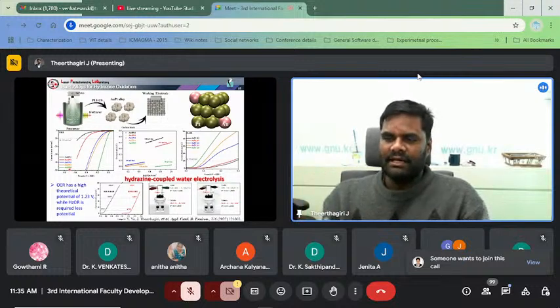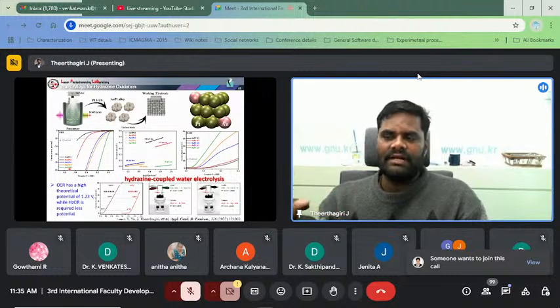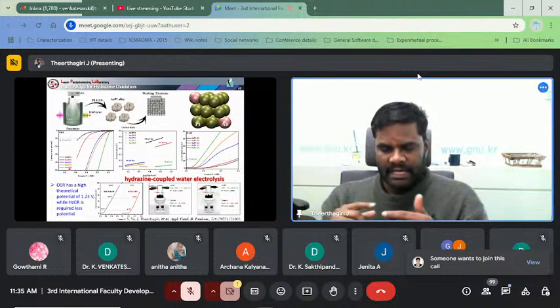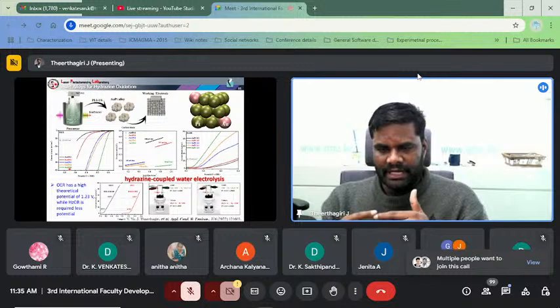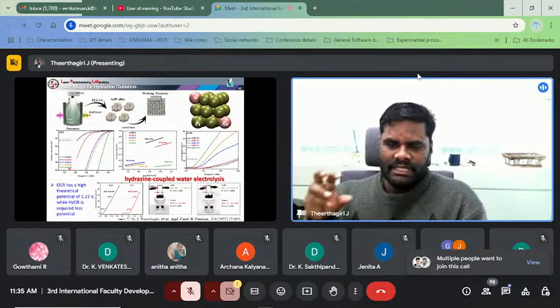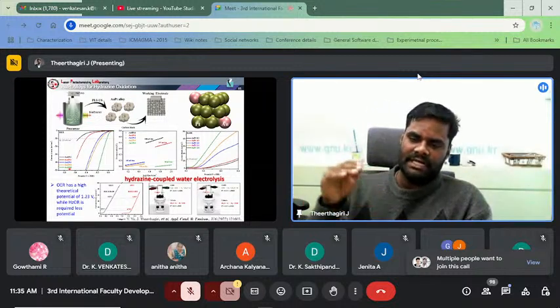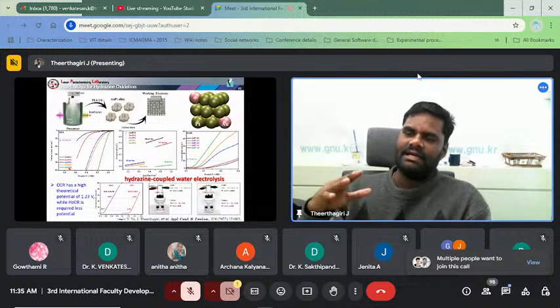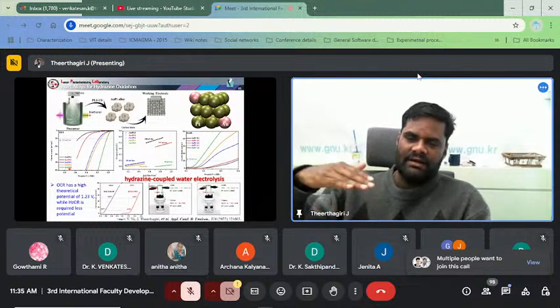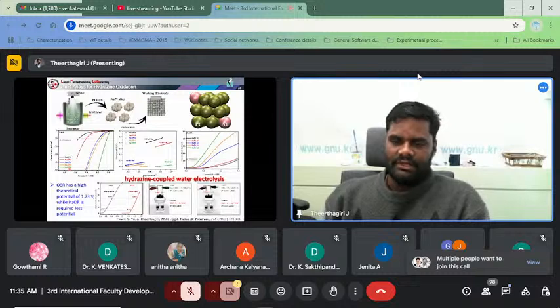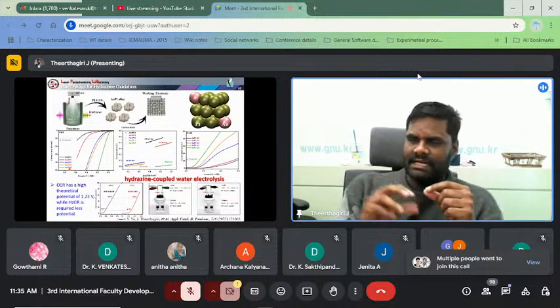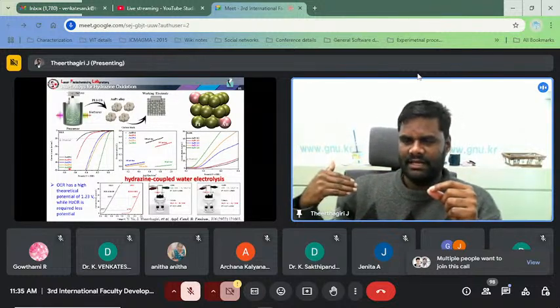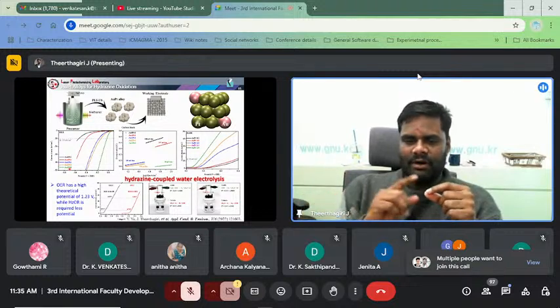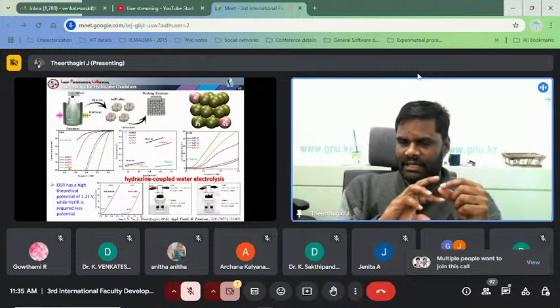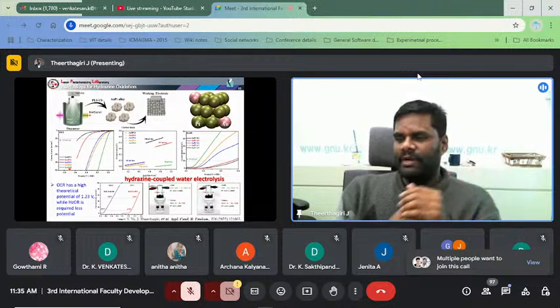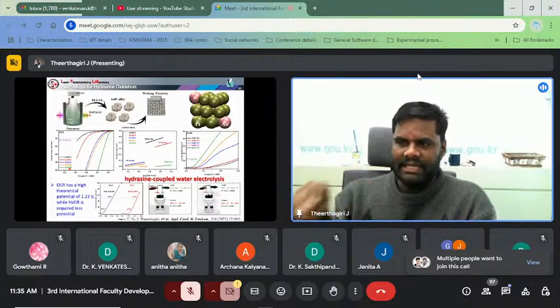The higher Pt concentration is not active for OER because during the electrochemical OER reaction, Pt is converted into PtO. This PtO, the surface oxidation state of this material, hinders the OER reaction. This is what we studied; maybe in the next slide we can show how we are studying the surface restructuring of the electrode material. That is our real research.